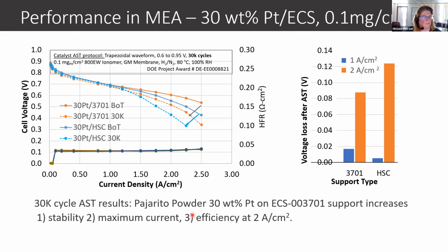So how do they perform in application? This is again some information that was collected at GM as part of our DOE project award in this area. And what you can see, for example, is that after 30,000 cycles of accelerated stress testing, our 30 weight % platinum on our ECS material increases the stability of the materials, enables maximum current, and also improves the efficiency at 2 amps per centimeter squared. And so what we have is some very, very good performing materials.